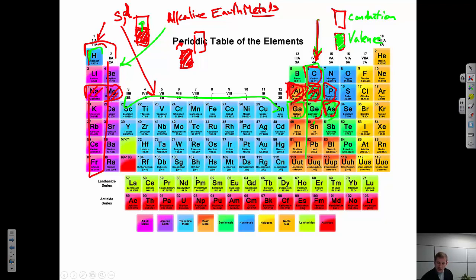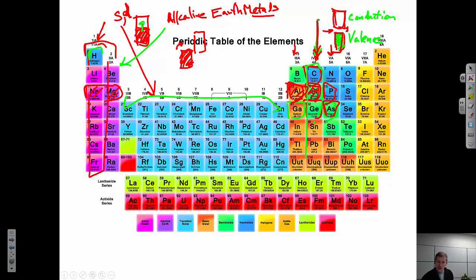We could call these the group four semiconductors — or combinations from group three and group five, which I call three-fives. But all of these lead up to the picture where I have a full valence band, some band gap, and an empty conduction band. The difference between all these semiconductors is largely what the magnitude of that band gap is and what is the nature of the electrons at the very top of the valence band or the free energy levels at the very bottom of the conduction band.